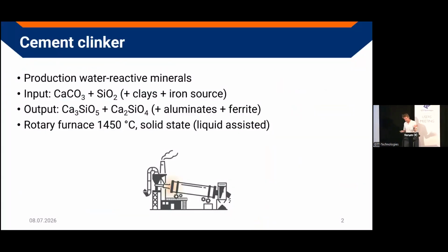So yeah, okay, I can actually skip this completely maybe, but the point for making cement clinker is that you make minerals that are reactive to water, like the C3S, the C2S, and the aluminates and the ferrites that Professor Peys already showed. So you start from calcium carbonate and the silicon, and then a little bit of clays, a little bit of iron, and you want to have the reactive calcium silicates and a little bit of the aluminates and the ferrite phase. Well, if a cement researcher says ferrite, it's not the alpha iron phase, but it's a calcium aluminate ferrite phase. And the cement clinker is produced in a rotary furnace, as we saw before, usually around 1450 degrees, although that depends a bit on the factory.